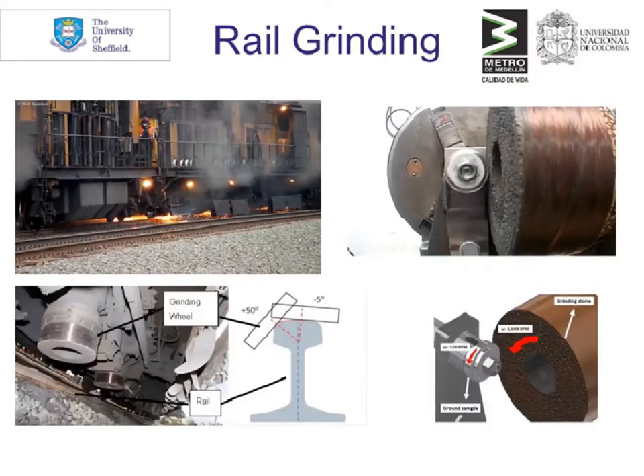So one way we can use to maintain good interface conditions for the wheel and rail, and one that's practiced worldwide, is rail grinding. So that's used to maintain the profile of the rail in its optimum condition. That gives contact conditions that should reduce damage and give better ride comfort for passengers in trains. But it's also used for removing damage that's accrued as well. So there may be cracks or dealing with high levels of plastic flow in rail or wear.